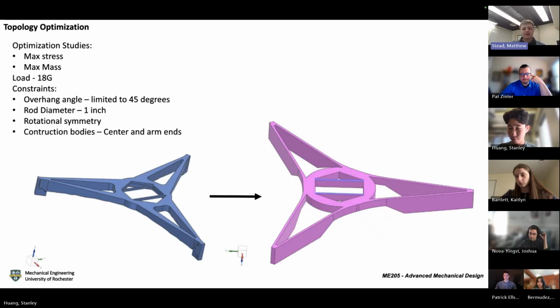Furthering on from that, we also did topology optimization to get an optimized shape for the design. So we ran studies on max stress and max mass. Because you can only include a more simplified load, we just did the equivalent of an 18G load vertically in the Z direction. And we used constraints such as overhang angle, rod diameters, rotational symmetry, and construction bodies. Then for the max stress optimizations, we also put in a mass target.